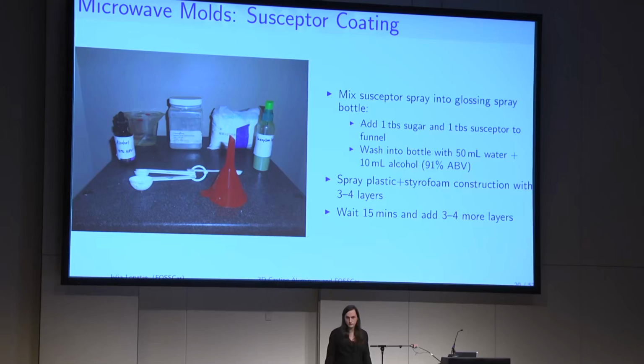We're looking at roughly 2 hours between the time in which we have a 3D printed part in our hand and the time at which we've got a mold in the microwave, versus the 8-hour approach of the standard lost PLA. So there's 6 hours of your life back, and probably a little bit cheaper life insurance because you don't have to use propane for this step.